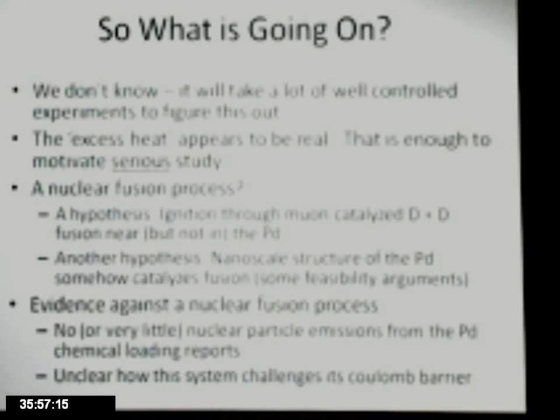Because if the muon comes and gets anywhere close to a positive palladium atom inside the solid, K-shell replace, it'll fall into a bound state with the palladium atom and never be seen again, and not available for fusion. So if, in fact, this is muon catalysis going on in the heavily loaded palladium of deuterium, it's going to be in some void region before the muon gets basically trapped in the palladium ion.